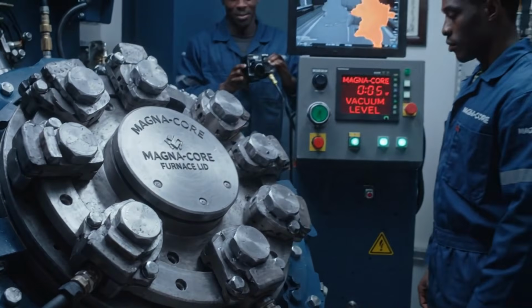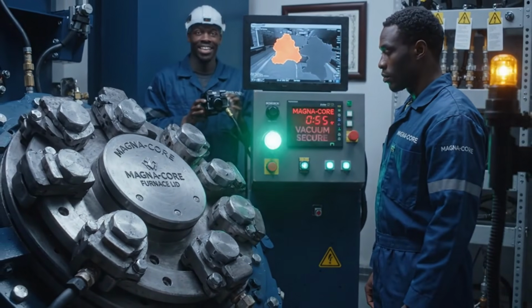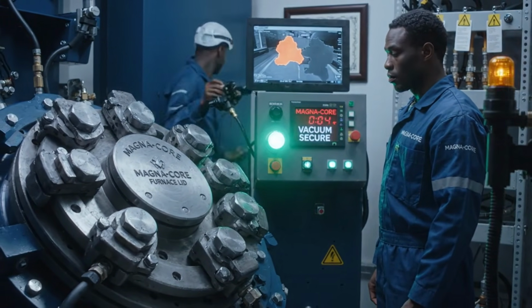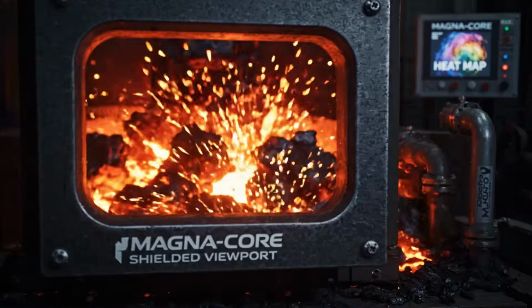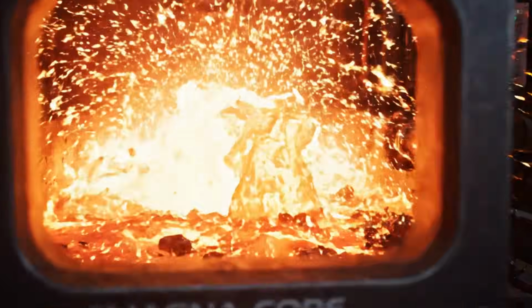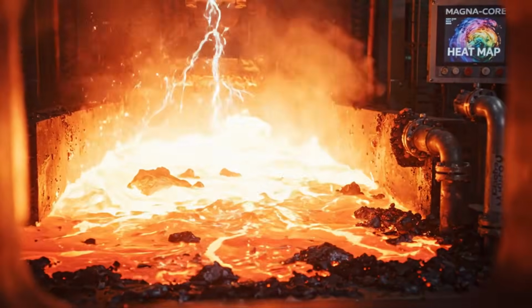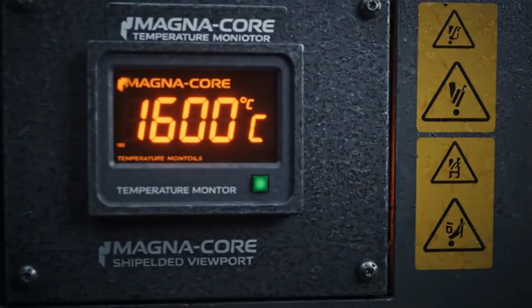A rack of green compacts is prepared for the sintering furnace, where heat will fuse the particles together. In a high vacuum environment, the blocks are heated to near melting temperatures to create a dense, solid material. For several hours, the magnets are held at precise temperatures as the atomic structures bond into a single piece.